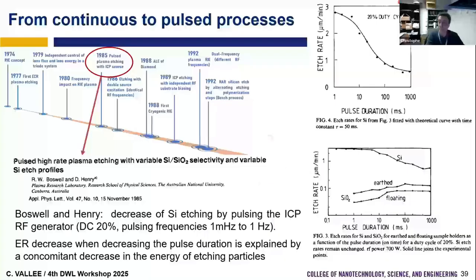And they observe that depending on the duty cycle and the frequency of the pulsing, we have no modification of the etching rate compared to a non-pulsing plasma, or we may have a strong modification of the etching rate compared to a non-pulsing plasma. And they observe that the drop of the etching rate is explained by a concomitant decrease in the energy of etching particles. So they say that as we pulse, the RIE effect is decreased because we decrease the